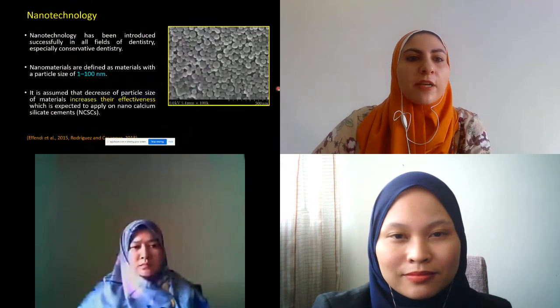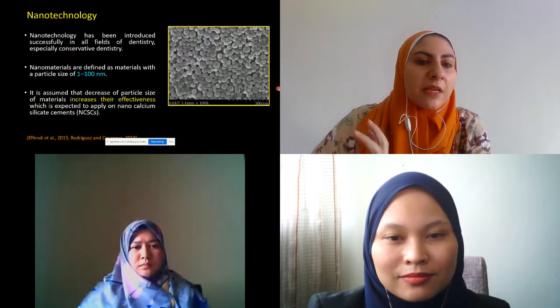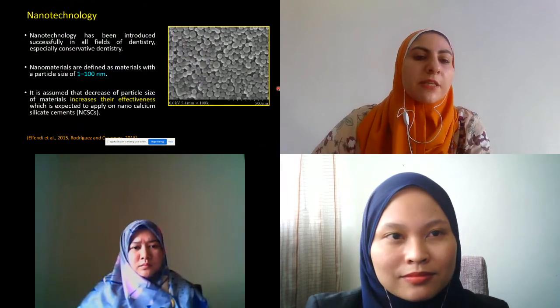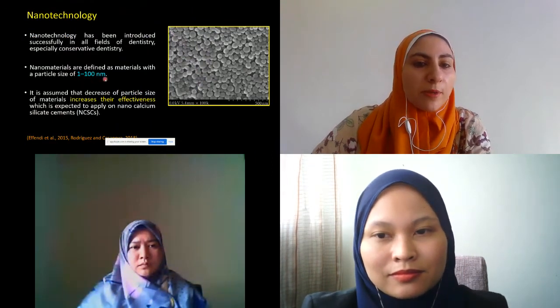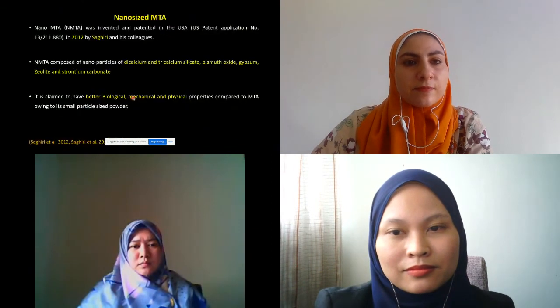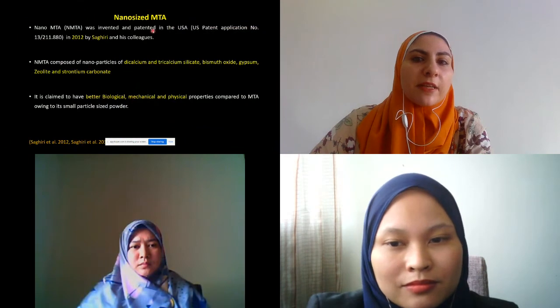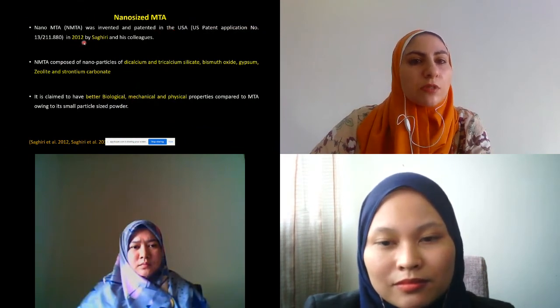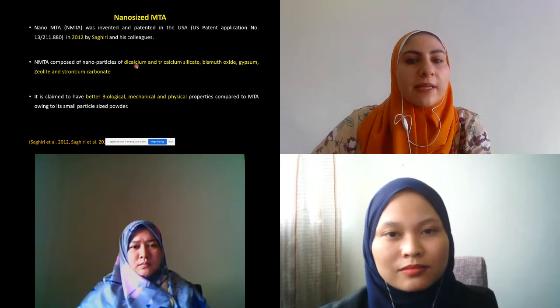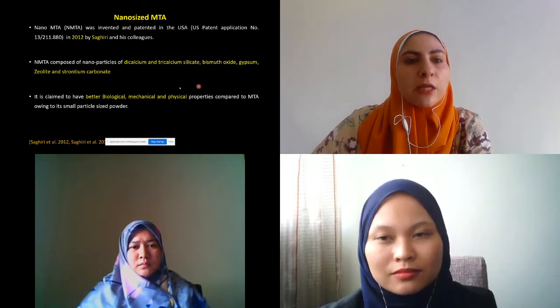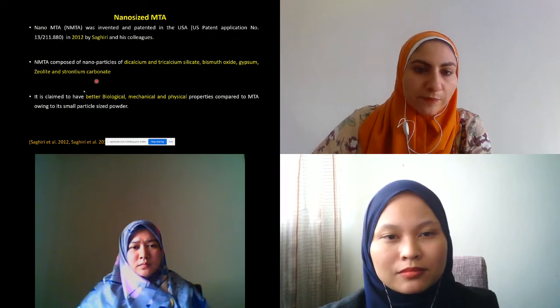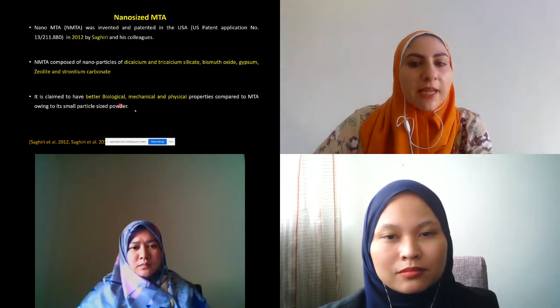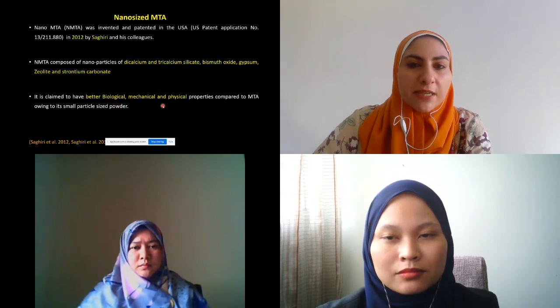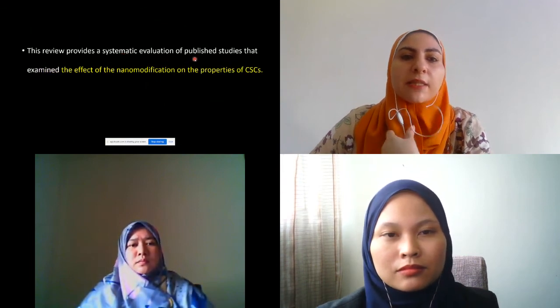So by the introduction of nanotechnology, we can see that if we make this material in the nano range of 1 to 100 nanometers, it can increase its effectiveness. Nano-sized MTA has been invented and patented in the USA by Saghiri in 2012. It is composed of dicalcium and tricalcium silicate, bismuth oxide, gypsum, zeolite, and strontium carbonate. It is claimed to have better biological, mechanical, and physical properties than the ordinary MTA. So this review provides a systematic evaluation of the published studies that examine the effect of nanomodification on the properties of calcium silicate cements.